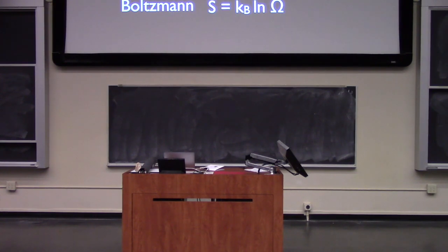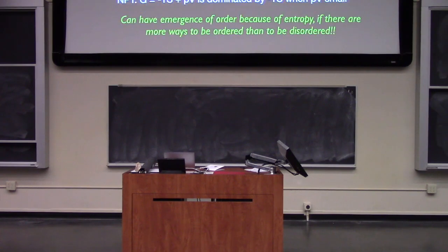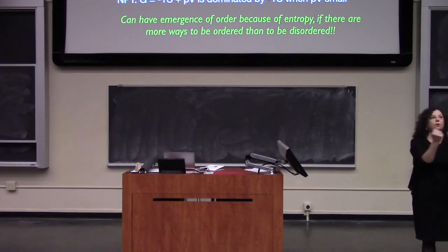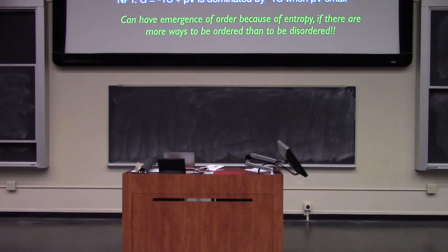expression, where it's just the log of the total number of microstates times a factor, gives you the entropy of the system. Now, in our system, we have no energy. I told you that it's 0 or it's infinite, so there's no potential energy in a box of hard particles. And so the free energy of the system is just the entropy of the system, but negative. So when thermodynamics wants to minimize the free energy, it's really maximizing the entropy, or maximizing the total number of microstates in the system.